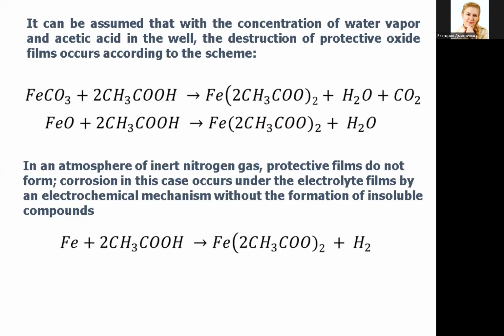According to Kuznetsov, the insoluble product of carbon dioxide corrosion located on the metal surface consists of oxide and carbonate of iron. It can be assumed that with the concentration of water vapor and acetic acid in the well, the destruction of protective oxide films occurs according to the scheme. In an atmosphere of inert nitrogen gas, a protective film does not form. Corrosion in this case occurs under the electrolyte films by an electrochemical mechanism without the formation of insoluble compounds. Thus, the influence of carboxylic acid in a field well in the initial period of development is reduced to the destruction of protective carbonate films formed as a result of carbon dioxide corrosion of the metal surface.